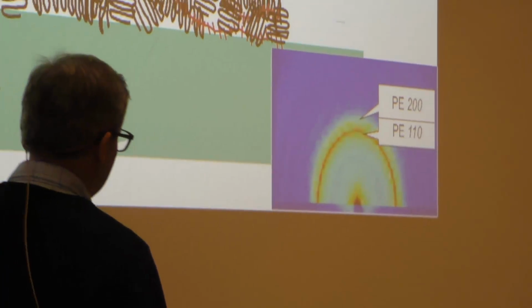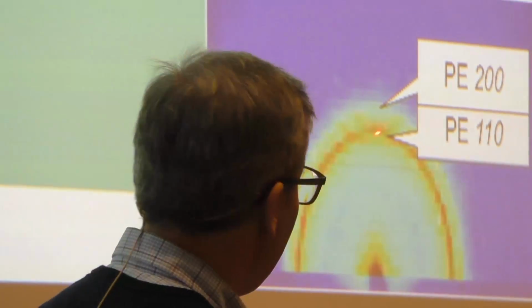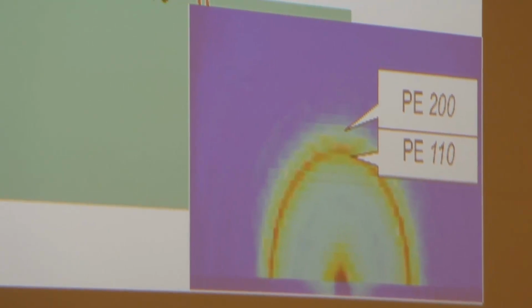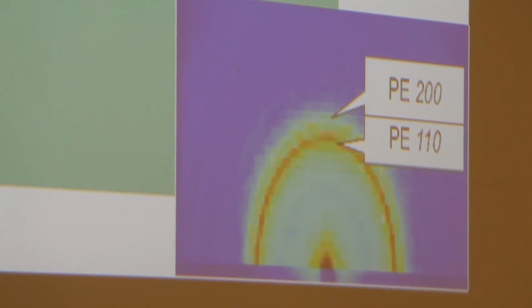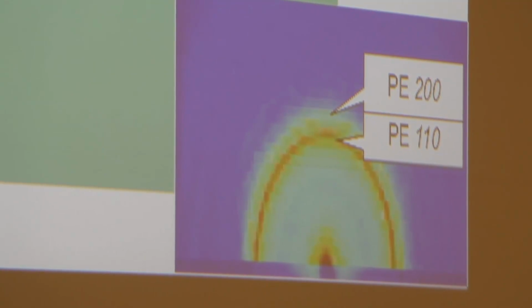And looking at the grazing incidence pattern, you can see that we have signals from polyethylene here, which is fully isotropic, meaning that the polyethylene crystallites here are randomly oriented. There is no signal from the polythiophene because the polythiophene has not been able to crystallize.